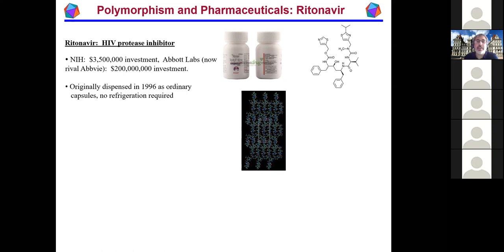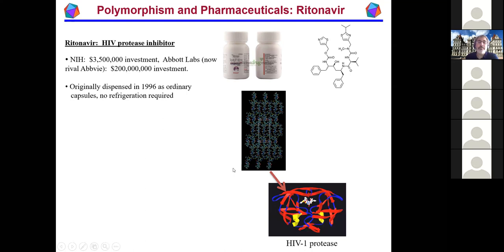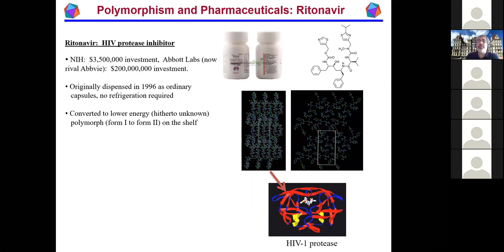Because at the time, they thought this was the only crystal structure that you had, all right? But what it does is once it comes apart, the molecules go in and they bind up the active site of the HIV protease, which is one of the proteins or the enzymes that is responsible for cleaving long polyproteins into active viral particles. Well, again, it turns out that if you just let this sit around, there's a late-appearing polymorph that shows up called Form 2, and it's very stable, and that means it's a very low free energy one, has poor solubility, and therefore it's not bioavailable.